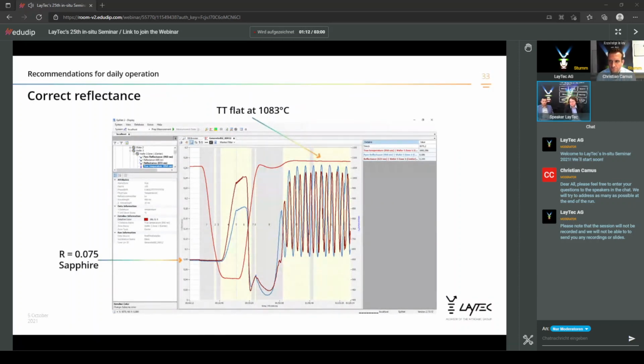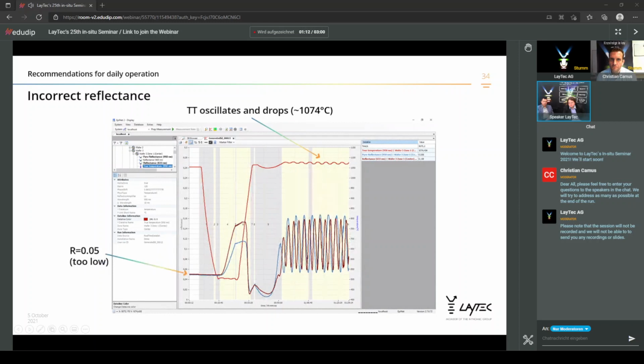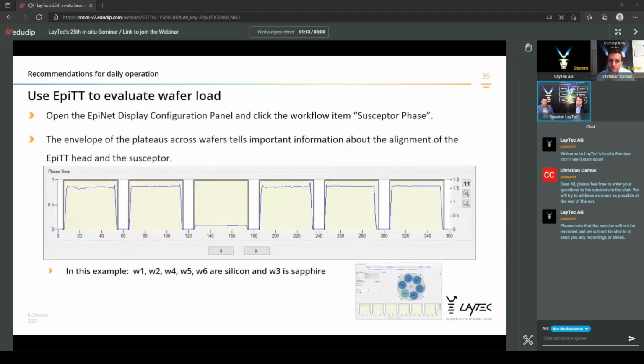So if we do the reflectance calibration properly, we will have a straight temperature line without any oscillations. If we do that with the wrong value, in that example set to 5%, even this minor change of the reflection will already cause some residual oscillations. So it gets very difficult to determine the real temperature value.